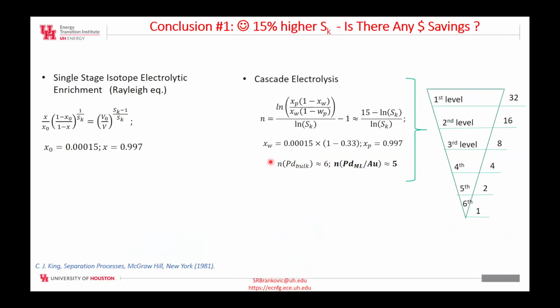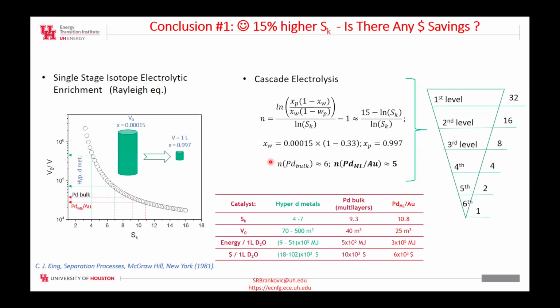Now, the question is how correct this is and how much relevance this has to an industrial or scale-up process. Here I'll give you two examples. One is the Rayleigh equation, which tells you that if you start with water, which has about 1.5 times 10 to the minus 4 fraction of hydrogen deuterium, and you want to enrich this water to 99.7% heavy water, you use this equation. If you want to get 1 liter of ultra pure heavy water, how much regular water you have to electrolyze depends on the separation factors of your catalyst. You can see the bulk palladium and monolayers in the middle. They are better than hyper D metals. But the best is palladium monolayers on gold, where you have to electrolyze 25 cubic meters of water, as compared to 40 for bulk palladium, or 70 to 500 cubic meters for hyper D metals used as a catalyst.